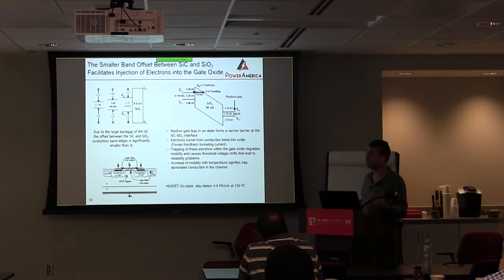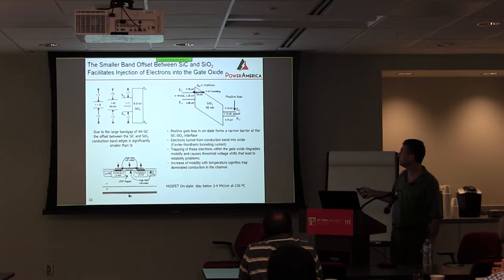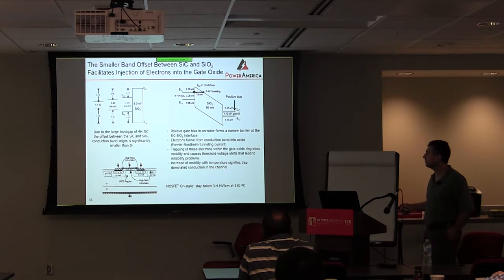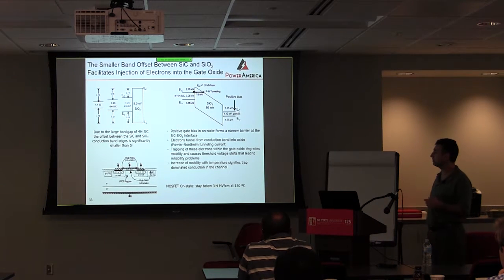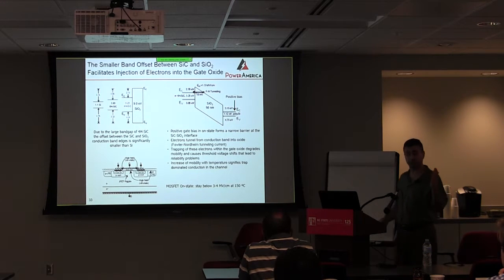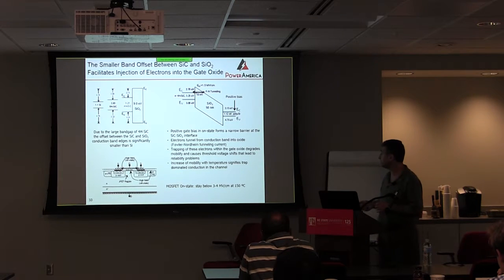That means that in the on state, when you turn the device on and the bands kind of realign, you can get tunneling from the semiconductor into the oxide. Okay, so electrons can tunnel from the conduction band into the oxide, and these electrons get trapped in the gate oxide, and that degrades the mobility, and it creates threshold shifts. Okay, so that's an issue. And of course it gets worse with temperature, right? Because the band gap changes.